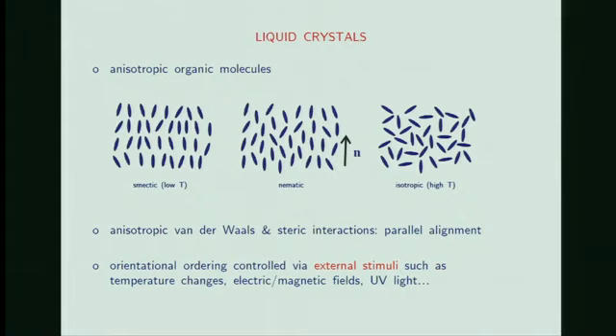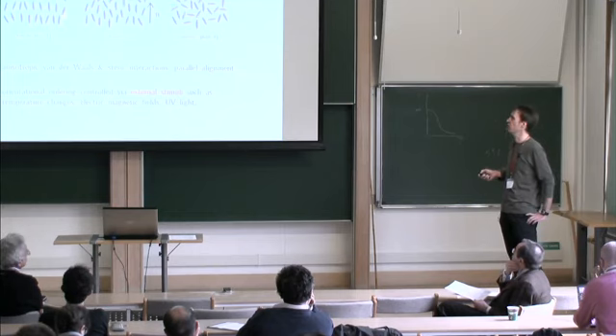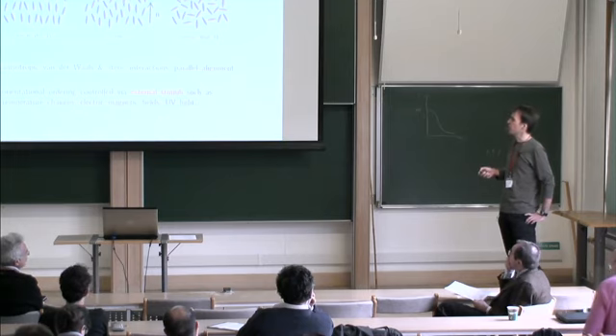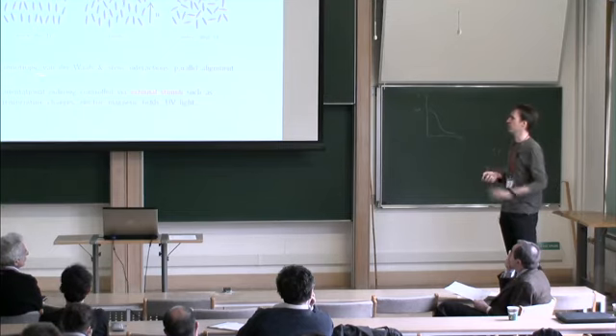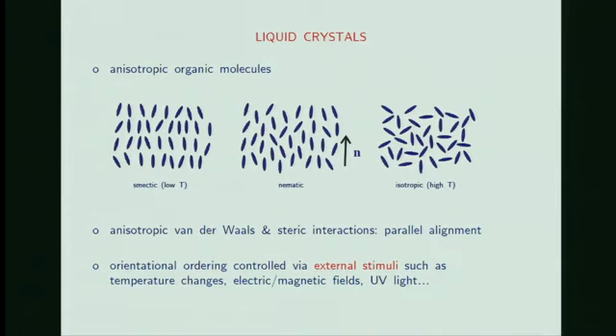Microscopically, in the case of ellipsoidal molecules, you can have such elongated molecules. In such molecules, you deal with anisotropic van der Waals and steric interactions, and they provide some parallel alignment that you can see here. What's important is that, as you know, the orientational ordering can be controlled by external stimuli: typically temperature changes, as shown here, but also electric and magnetic fields, but also ultraviolet light.